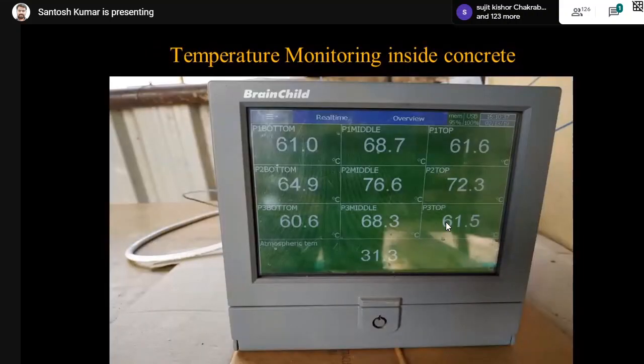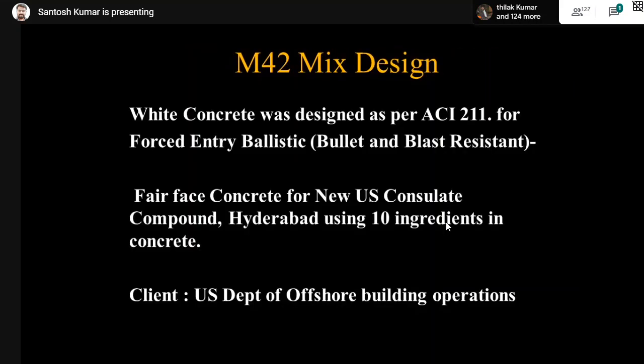And temperature monitoring inside the concrete also developed, because if you use pure OPC for at least M40 grade concrete, the temperature inside core concrete may shoot up to 100 degrees also. So the importance of monitoring the temperature of the concrete has also taken pace.